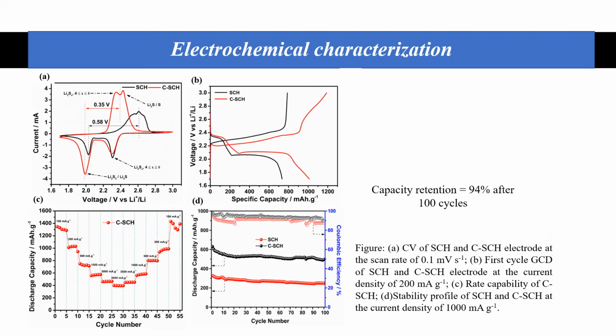Later, the electrochemical characterization was carried out on the as-prepared electrode. Figure A is for cyclic voltammogram performed at 0.1 millivolt per second. In this case, we can see the area under the curve of the red plot is higher as compared to the black plot. The red plot is for the carbon coated sample. Here we can see with the use of carbon coating, there is an improvement in the charge storage capacity. The same thing was communicated when we performed the charge discharge profile at 200 milliampere per gram, where we can see the capacity enhancement due to the carbon coating.